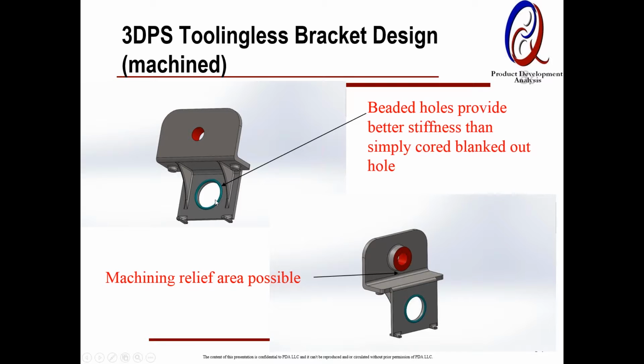Stiffeners on both sides. They wanted a relief area. We were able to do that, and also this is from my experience making locomotive truck frames, where if you just have a regular hole, a cored hole, you lose the material and the stiffness. You can regain some of that by putting a bead on both sides of the cored hole.